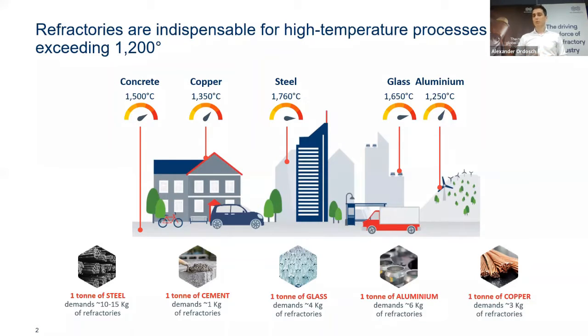Basically, all metal production involves consumption of refractories. In the slide, you see four metals and cement or concrete, which all use refractory products with varying specific consumptions and varying temperature resistance. If you want to produce 1 ton of steel, for example, you need around 10 to 15 kilograms of refractories with a heat resistance up to 1760 degrees. That's on the higher range of the temperature range for refractories. If you go to the very high grade refractories, then you can manage temperatures just above 2000 degrees. So don't mix up a refractory with, for example, a special ceramic. If we talk about some nitrogen compounds with metals, these are not refractories, those are ceramics. So think of refractories as really a mass-produced product out of a mineral raw material. And about these raw materials, I want to talk later.